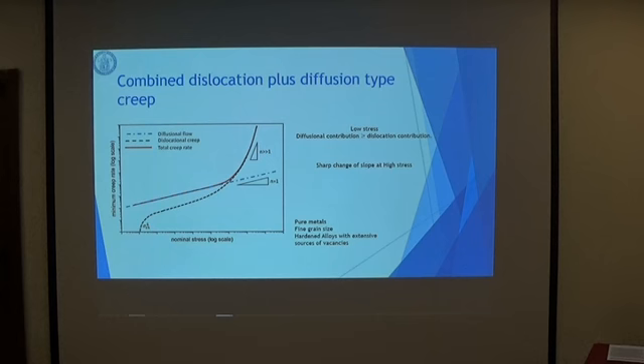The second situation is when the diffusional contribution is equal or greater than the dislocational contribution. And we can see that going from quite low stress level to quite high stress level, there is a sharp change in the slope of the total creep rate. This is a typical behavior for pure metals having fine grain size and hardened alloys with extensive sources of vacancies.